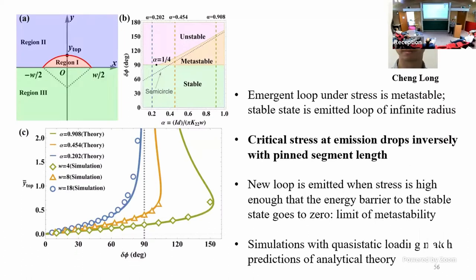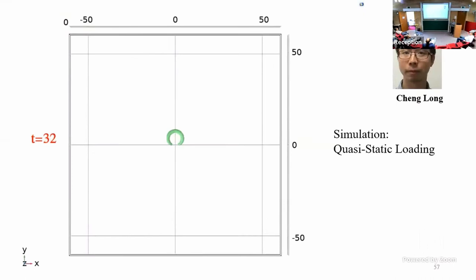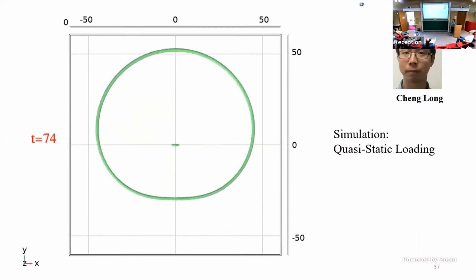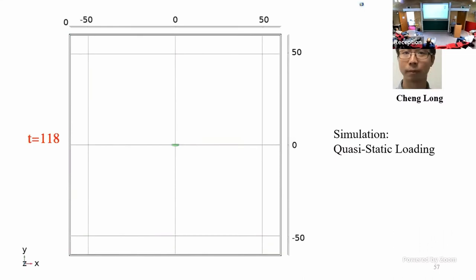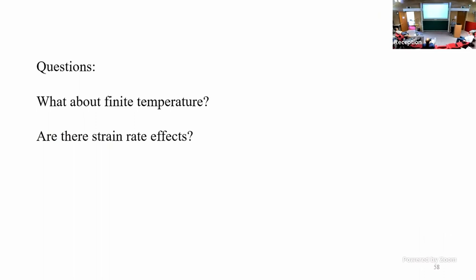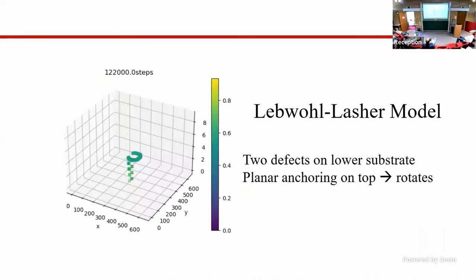So here is Cheng's simulation. This is a quasi-static loading, meaning he applies the twist and just waits. So it's not a continuous strain rate, but you can see the defect coming out and snapping off. And if you keep going, every 180 degrees you get another one. Okay, my student Matthew Deutsch wanted to do the finite temperature, finite strain rate version. I'll just show you a quick video so you can see, same story. Here at the top and bottom, this is hugely stretched, but there's an arch and then defects pop off.